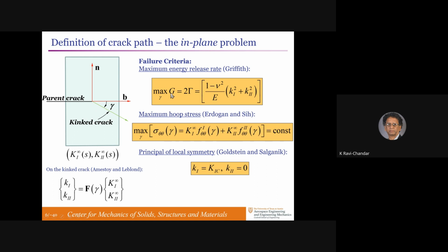And that's written here. The maximum of the energy release rate over all angles gamma must equal the fracture energy of the material. But you can get an explicit formula for the maximum energy release rate in terms of the stress intensities experienced by the kinked crack, through a calculation that was demonstrated by Hutchinson and Suo, that the local value of the stress intensity factor, local to the kinked crack, in terms of the global values of the stress intensities, is some function of the angle gamma, right? And so you can do this calculation, find the angle gamma at which maximum energy release occurs, and pose the fracture criteria. There are other possible criteria: maximum hoop stress, which is just a stress calculation, find sigma theta theta as a function of angle, whatever angle theta gives you the maximum, that's the angle in which the crack would grow. And the last criterion is the principle of local symmetry.